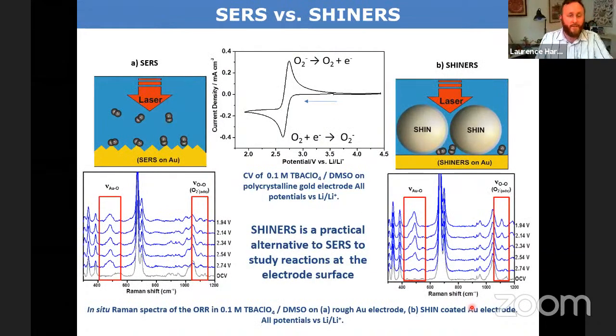And in particular, we've used SHINERS to look at, for example, in this example here, superoxide forming at the electrode interface, and we're comparing traditional SERS here. So we have our gold-oxygen band, which is growing as we reduce the oxygen and form this superoxide. So we have very nice correlation between the electrochemistry and the spectroscopy.